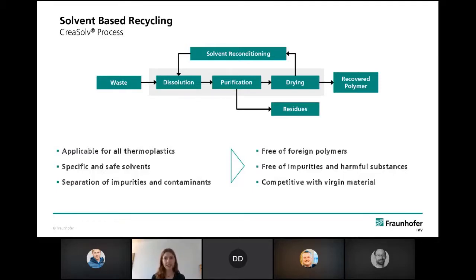The CreaSolv process, as it is depicted in this picture and as I explained it to you now, was the, let's call it, classical CreaSolv process. In this way, we use it, for example, for packaging waste, for example, mixed packaging fractions that cannot be sorted any better, or where we have multi-layer packages that cannot be recycled either. And in those fractions, we usually have, for example, polyethylene, which has the highest amount in those fractions. And then we would dissolve the polyethylene and regain it from the solution.